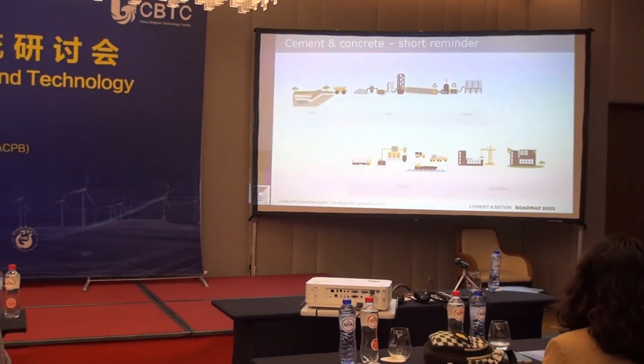Right. Okay, just as a reminder, to produce concrete and cement, making the difference between cement and concrete is not always clear for everyone. We start from a quarry, quarrying the limestone, and then this limestone is crushed and introduced into a kiln. There are actually two chemical reactions. The first reaction is called the decarbonization, at a temperature around 850 degrees. The calcium carbonate, the limestone, will transform into calcium oxide and CO2. This is a chemical reaction, and this is unavoidable. You cannot do without this in your process to produce what we call the clinker. The clinker is the active part of cement. The first reaction is the process reaction, and then there is a clinker reaction where the calcium oxide will combine with the iron oxide and the silicate to form this famous clinker.